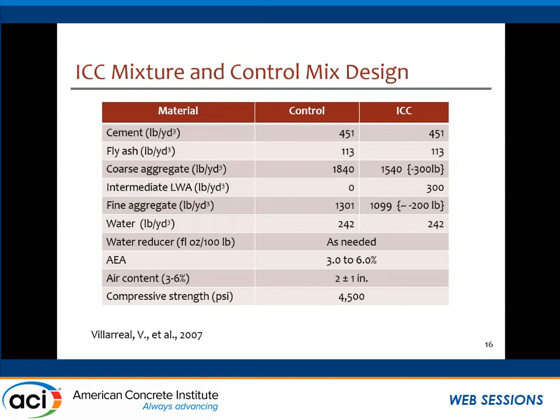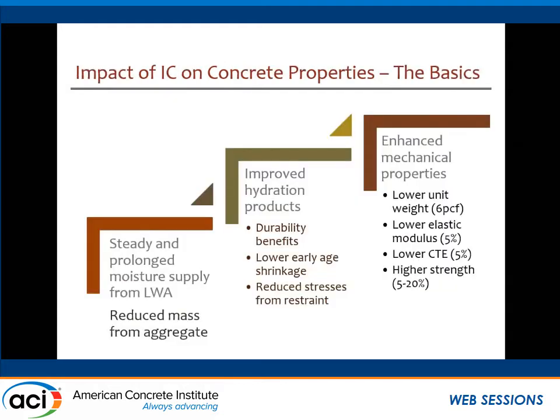So what you've essentially done in this mix design, compared to the conventional mix design, is taken off about 500 pounds and added 300 pounds of lightweight aggregate. But remember, you're replacing equal volume, so you're taking off a higher weight of aggregate. Everything else remains the same, including the amount of water. In this case, they were able to meet the specification requirements, 3 to 6% air, and the compressive strength was a 4,500 psi target strength.